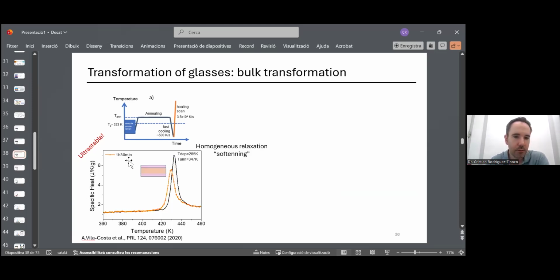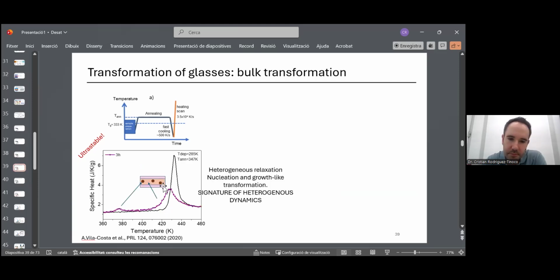formed. If we, instead of 30 minutes, now have 90, an hour and a half, still more change in the glass, but no traces of liquid. Now, 3 hours. At 3 hours, we see a change in the glassy peak, but we see here some amount of fast cool glass. Okay, so it means that some regions of the glass during this annealing have transformed into the liquid state, and when we perform the measurement, this is manifested via this devitrification peak of the fast cool glass. Okay, so we have some fast cool glass, and we have some still glass that has been changed with respect to the initial glass, but still a glass. Okay, glass that has not become a liquid during this process.